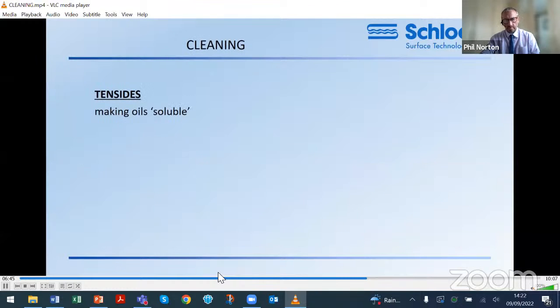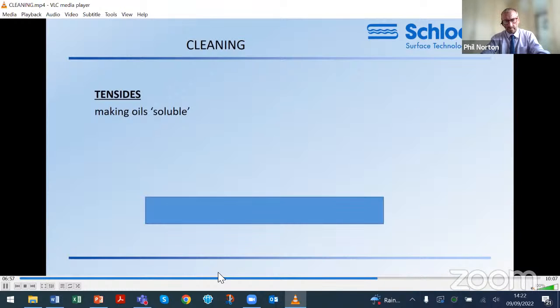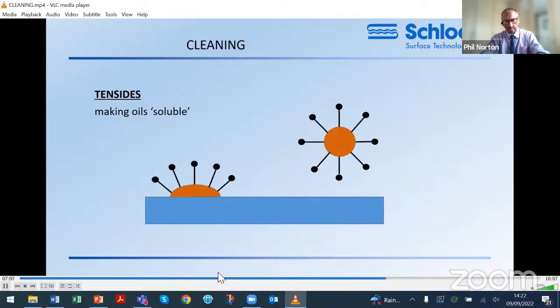Tensides are synthetic organic compounds with interesting chemical characteristics. They can coat oils and grease and make them effectively soluble. In this idealized model, the substrate which needs cleaning may have oils on the surface. The tenside molecules attach to the oil and then form a layer around the oil to hold it in solution.